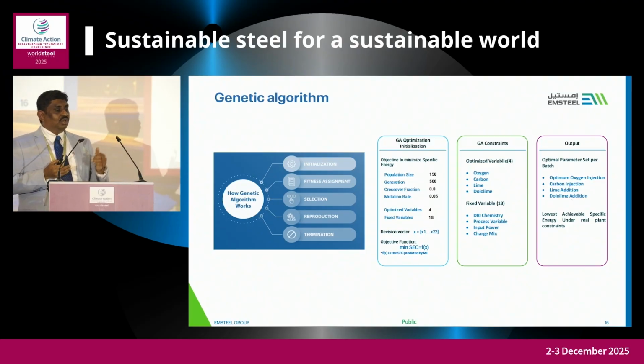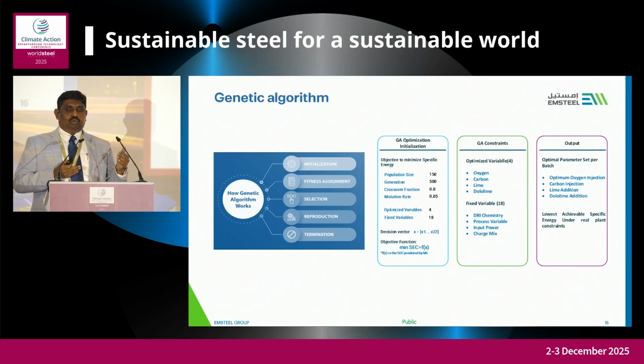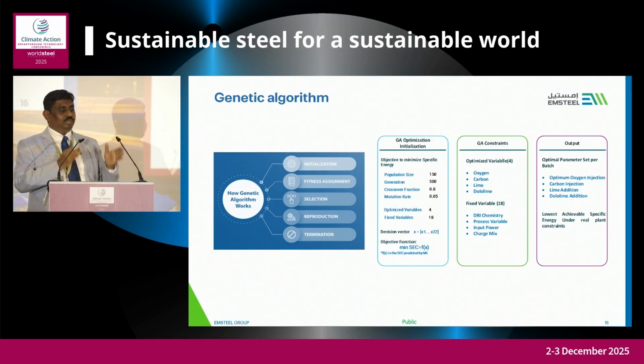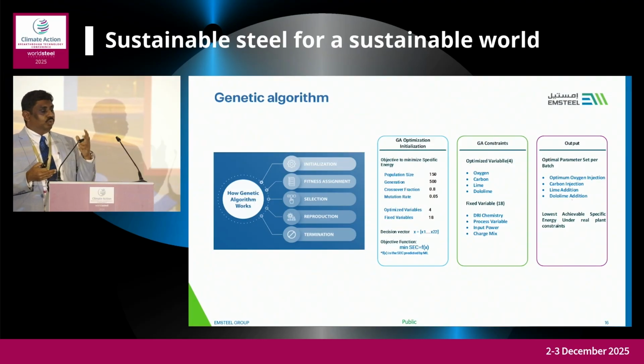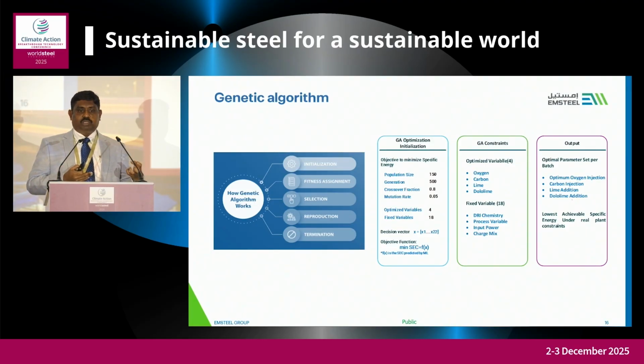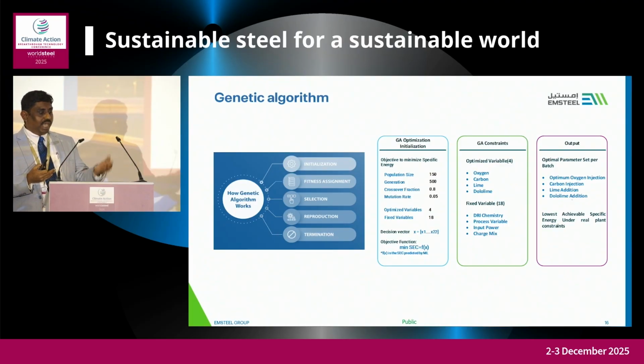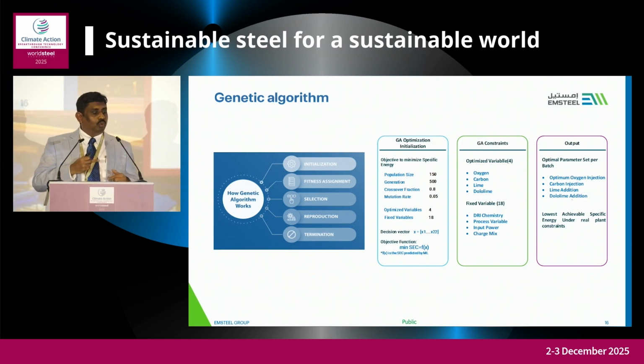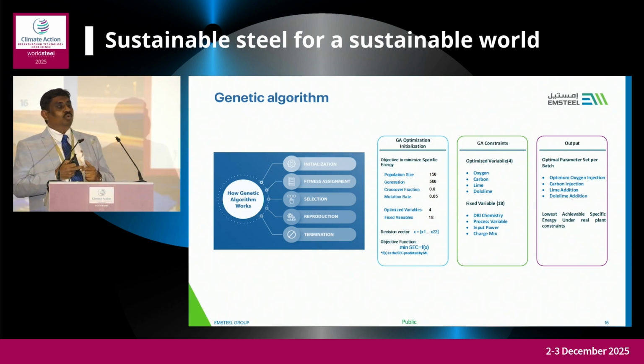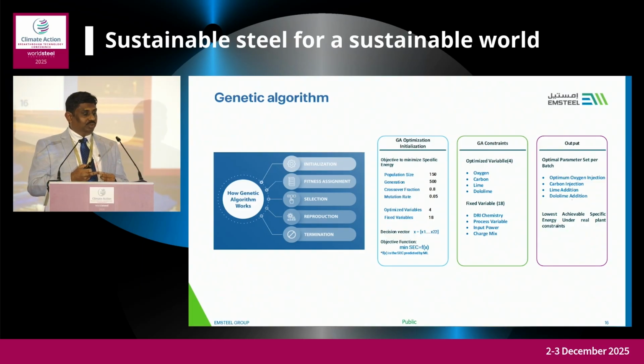Out of this, some parameters which are not controllable, we consider as fixed variables. Parameters under the control of the operator, we consider as variable parameters. So we put the same range, minimum and maximum range of the optimized value, to run the genetic algorithm to minimize the energy. And here, if you see, this will optimize the oxygen injection rate, carbon injection rate, lime and dolomite injection rate to minimize the energy consumption.